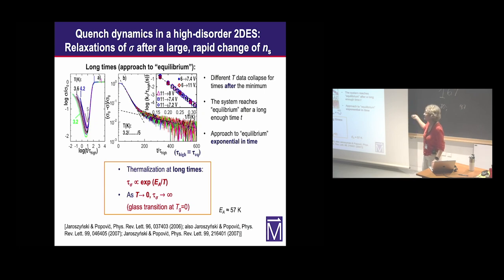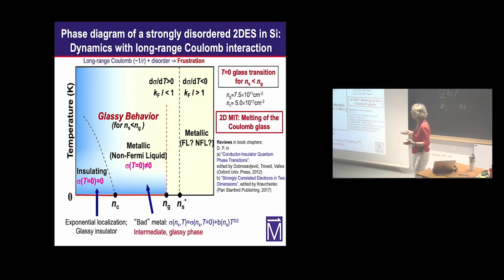We have studied this glassiness using also other protocols similar to what people do in other types of glasses, like spin glasses. This is a sketch of our conclusions. There is a well-defined glass transition density, below which there is a zero temperature glass transition for each of these densities. So this insulating phase is glassy, and this intermediate phase is also glassy, but they're not the same kind of glass. At low enough temperatures, on short enough time scales, we see glassy behavior. At a temperature of about 1 Kelvin, the thermalization time is actually orders of magnitude longer than the age of the universe. So it doesn't really matter that we are not truly in the glassy regime, which occurs at zero temperature, because on experimental time scales, the system is glassy.